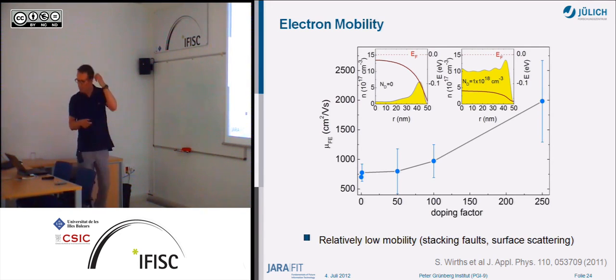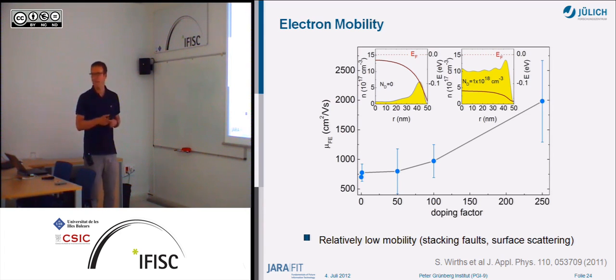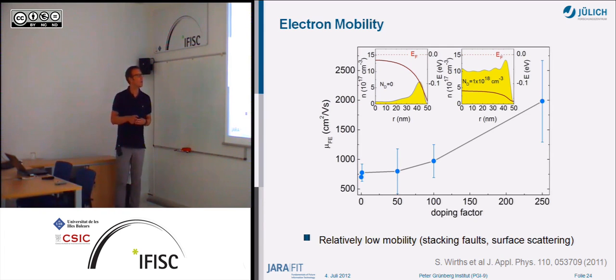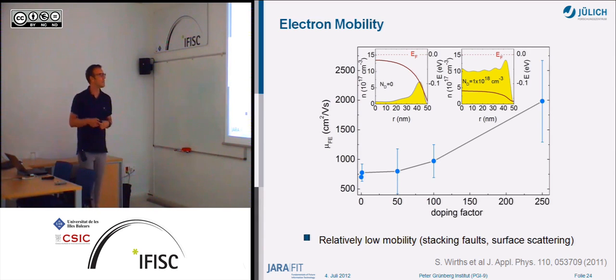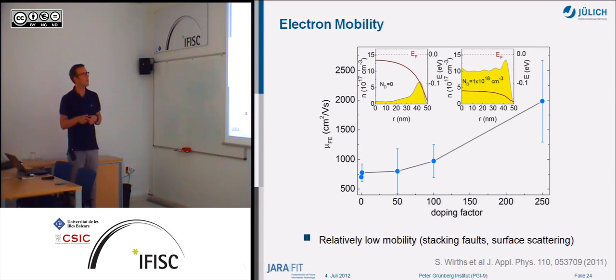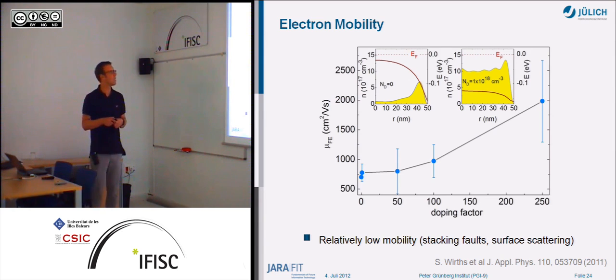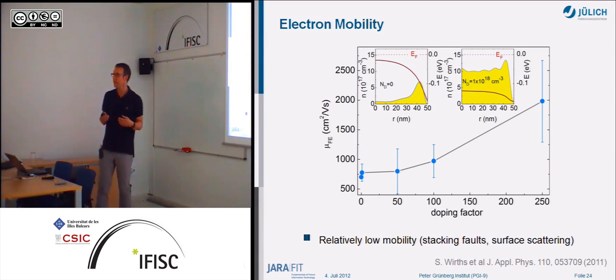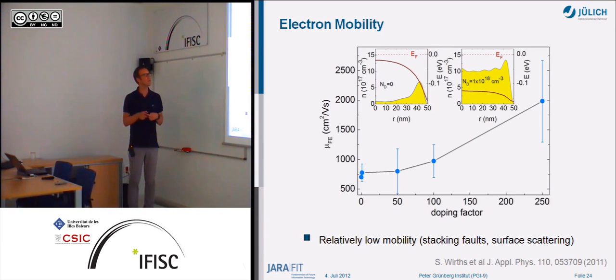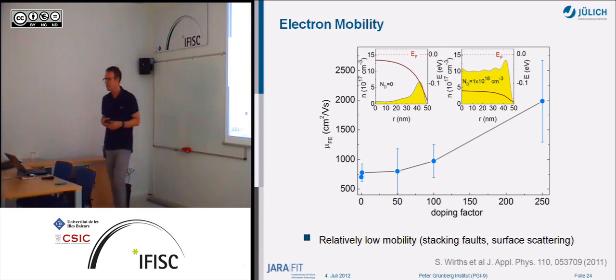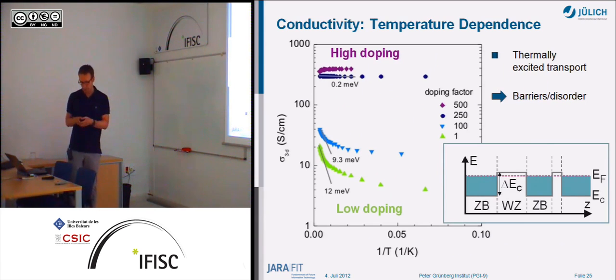And what we think of is that if you increase the doping, what happens to the electrons? If you look here, this is the electron concentration, this is the border of the nanowire, that's the axis of the nanowire. If you have almost no doping, you have an accumulation layer right at the surface, as I explained before. So you have a lot of surface and interface scattering, because the electrons are directly seeing the interface here. But if you have a large doping, if you do a calculation with the Schrödinger-Poisson solver, you see that the electrons are flooding the complete nanowire, and then you have less scattering because a lot of electrons are in the middle of the nanowire, and that's why the mobility increases. That's at least what we think of this here.